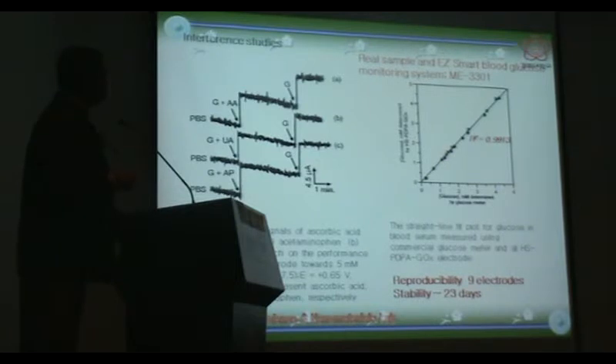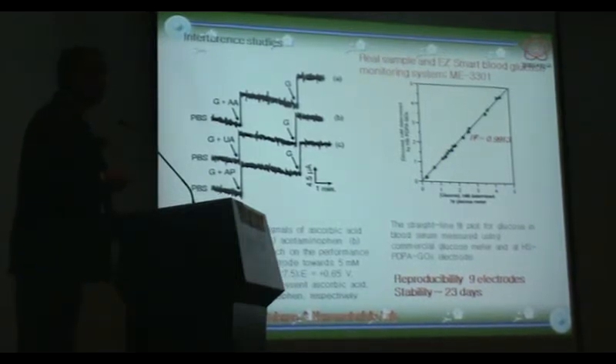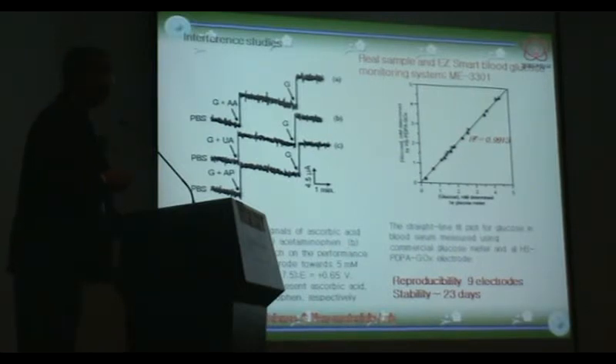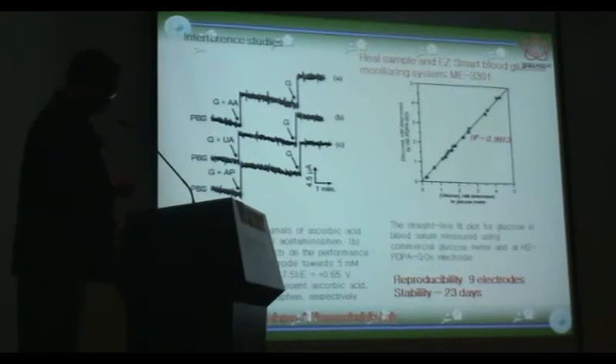What is more important is we checked the practical viability of our electrode using real blood sample analysis, and we compared with the values obtained with the help of an existing glucometer. Okay, so we made a straight line fit between the values determined from the real glucometer available in the market, and values determined by our own sensor and approach. So the closeness of the fitted values clearly says that this kind of material is ideally suited for commercial glucometers. And the reproducibility and stability were also checked.